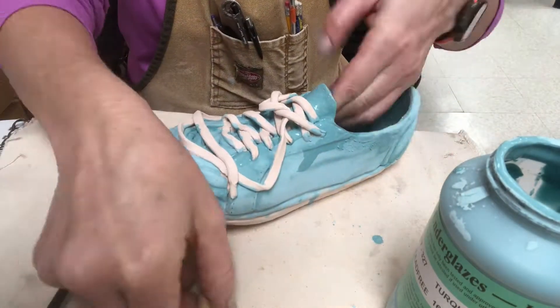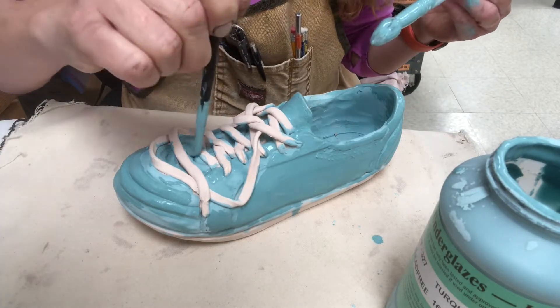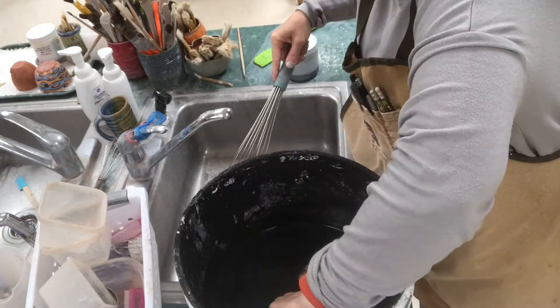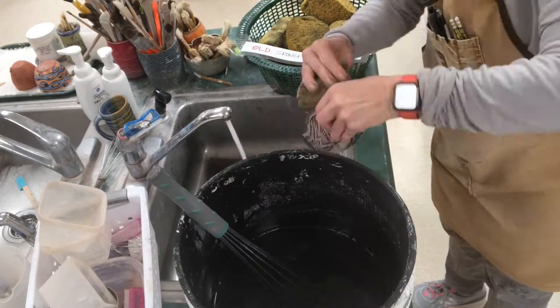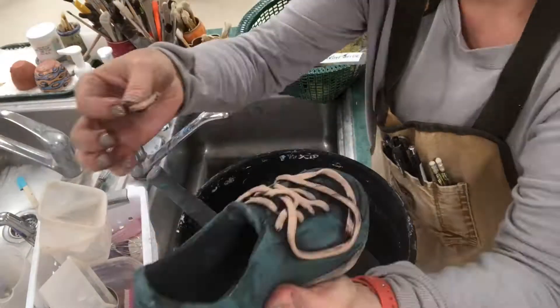This is moderate difficulty because I'm trying to avoid the laces. I'm applying three to five coats. If you want it more sparse where you can see through it, you could do two. The underglaze then gets bisque-fired for the second time, and after that we apply the iron oxide again — either brush it or dip it just like on the boot, then sponge it with a clean rinsed-out sponge. You get great iron oxide detail in the textures, and then it gets fired to a mature glaze firing temperature.